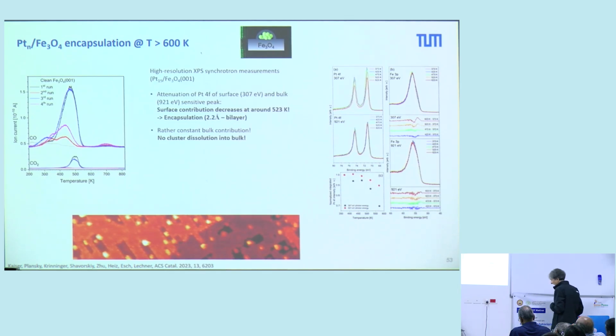But you can also use XPS, and you see here XPS of platinum, the surface sensitive peak and the bulk sensitive peak, and you see indeed that we have a decrease of the feature of platinum in the temperature range where we observe this SMSI, this encapsulation. The bulk sensitive peak does not change. That means the clusters do not diffuse into the bulk. But we can also look at the iron oxide, and you see a very small feature here. And if you take the difference spectra, you see indeed that we have a feature growing in, which is typical for iron oxide, iron 2+, at the expense of iron 3+. This is another indication that we have this very thin film over these clusters.